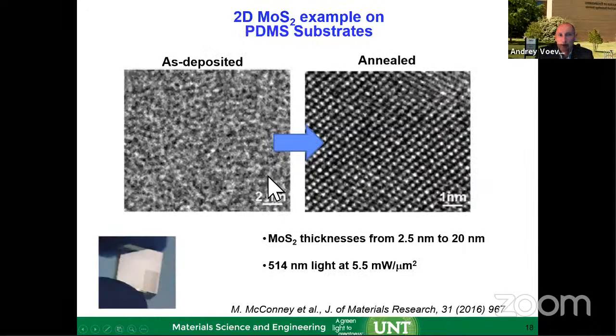And if we do the TEM analysis, as deposited is amorphous, but if we focus on that one channel annealed, you see a well-developed hexagonal structure of the material formed in here. So you can convince yourself, okay, that during this annealing, right over here, I made that hexagonal material semiconducting.